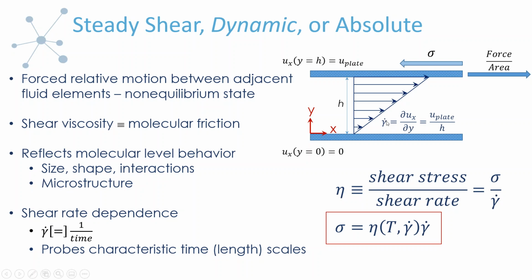So the shear rate, what is that in this particular flow channel? This is defined as the velocity gradient perpendicular to the direction of flow. So what happens when we are shearing the fluid by moving the upper plate is that we set up this velocity profile. And what we see is the velocity is only non-zero in the x direction, and it varies only in the y direction. And so we have a gradient in the velocity in the y direction, which is the direction perpendicular to flow. And that's how we define the shear rate. And it's very simple to calculate for this type of flow field, and it's in fact a constant. It's just the velocity of the upper plate divided by the fluid gap height.